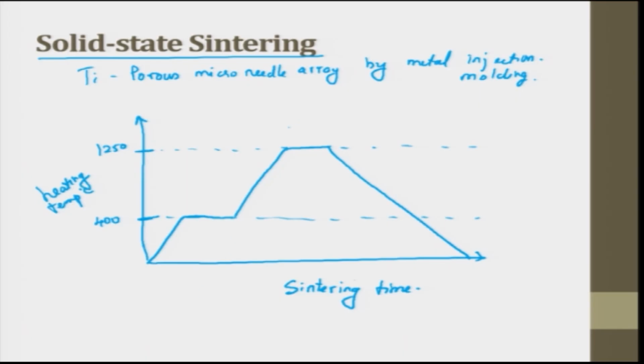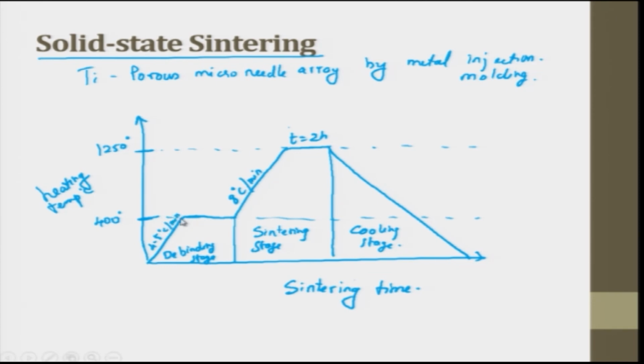So, here what we do is we divide it into 3 stages. The first stage is called the debinding stage. The next one is called the sintering stage, and the last one is called the cooling stage. Here you hold it for 2 hours at 1250 degrees Celsius. Here you increase at 8 degrees Celsius per minute to reach this. Here you take 4 to 5 degrees Celsius per minute, and here 2 to 3 degrees Celsius per minute. So this is a typical sintering cycle.